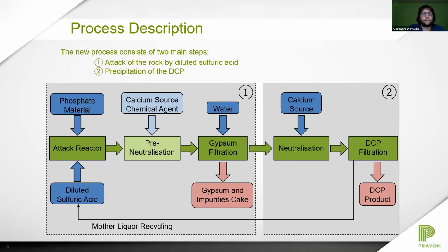We have first an attack of the phosphate material by sulfuric acid in diluted conditions. The goal is to produce a mixed solution of phosphoric acid and monocalcium phosphate. With this solution, we can adjust some process parameters and reduce the fluorine content, for example, or heavy metals. This is called pre-neutralization. Then we make a filtration of this slurry, and the filtrate will then be neutralized with a calcium source to produce a DCP that will be the final product.